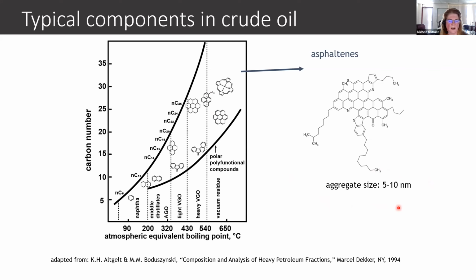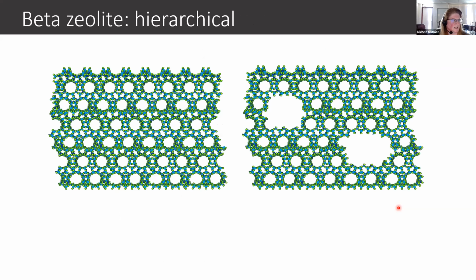And so what you have is a gap between the size of the molecule that needs to be able to go into a zeolite pore to have chemistry performed on it, and the actual physical pore dimension of the zeolite itself, which then leads us to being able to engineer ways to make hierarchical zeolites. And so on the left-hand side, we have our traditional beta zeolite, which has micropores of less than 2 nanometers.